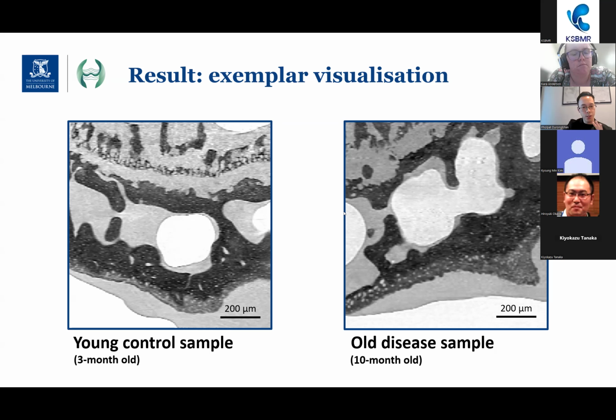But just to show you here, you can see that in the younger control sample, the porosity looks normal, quote unquote, whereas in the older model, you can see that increased porosity and the thickening of the low mineralized layer as we typically observe in an osteoarthritis model. But then how do we put numbers to these things?